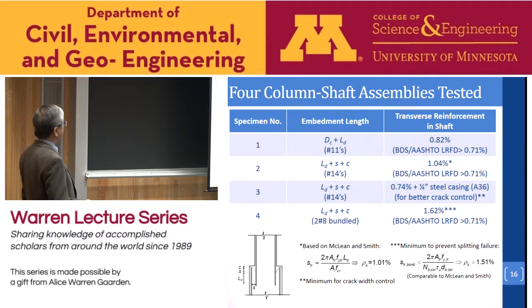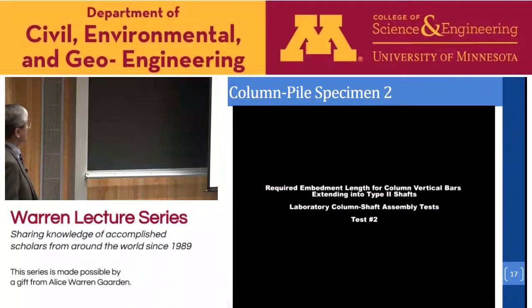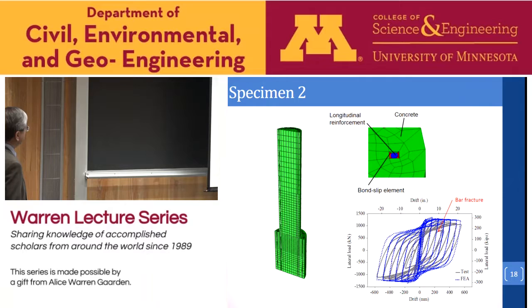And for the last two specimens, we use the confinement reinforcement based on the formula we propose in this study. This case really provides the minimum to prevent the splitting failure, and this one is the reinforcement required to control the crack width introduced by the tensile splitting due to bond slip. So what I show you is test number two, the second specimen, which used the embedment length and also the confinement recommended by McLean and Smith.